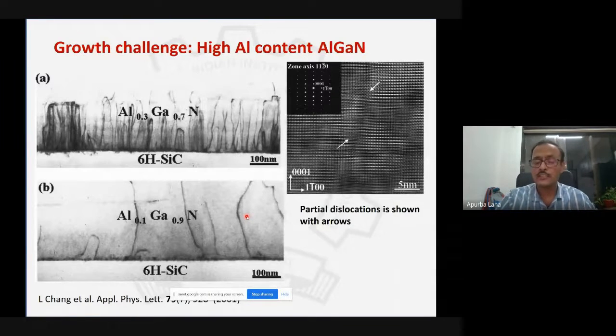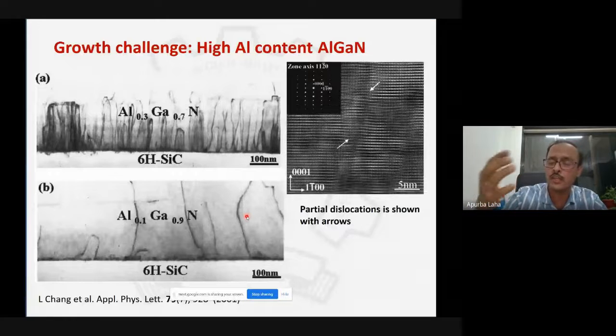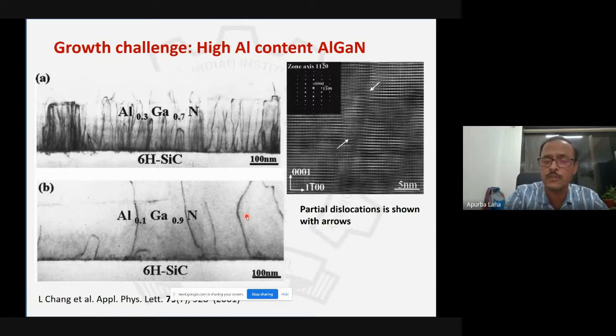So there are challenges when you are looking at gallium nitride based devices. When you are talking about light emitting devices that require emissions in the range of 300 nanometer and below, you have to incorporate aluminum into gallium nitride, and that makes things much more complicated and challenging. Today, with the aluminum nitride or aluminum gallium nitride based UV LEDs that are available, although if you can create single crystals you will have a very bright UV LED, with the current quality of the layers we can only achieve maybe a maximum of 20% light efficiency, for example. Those are the challenges when you grow.